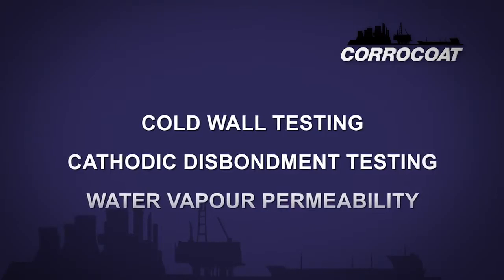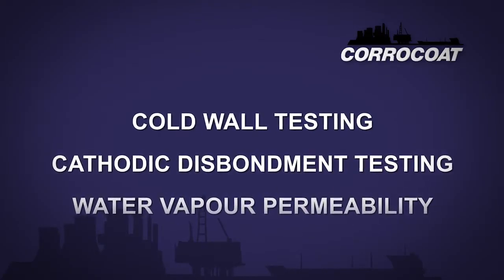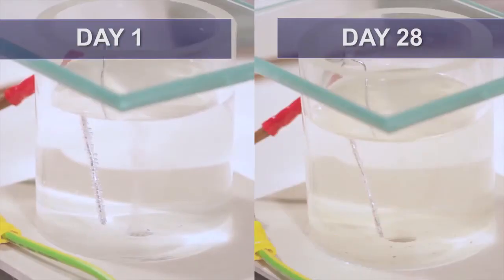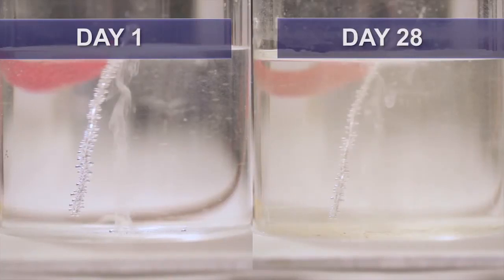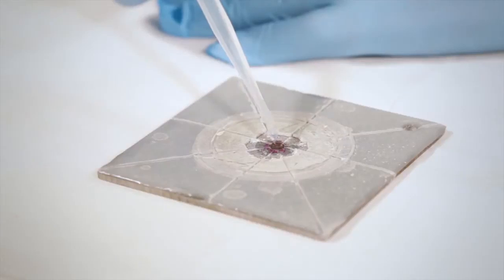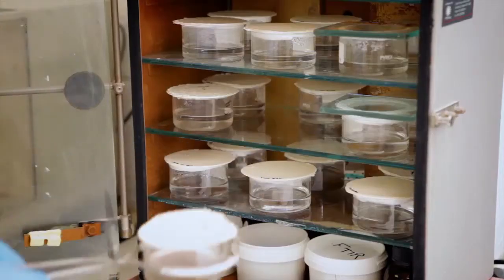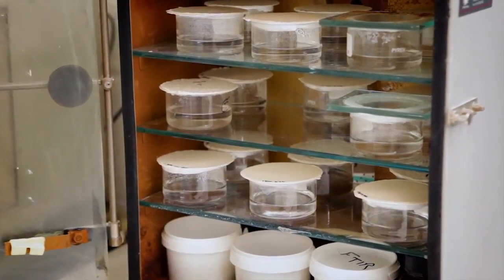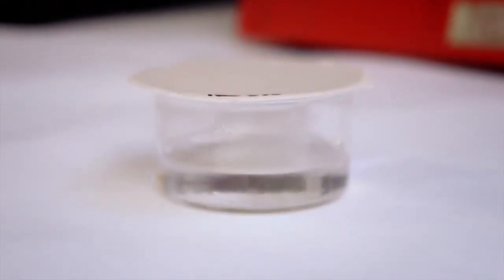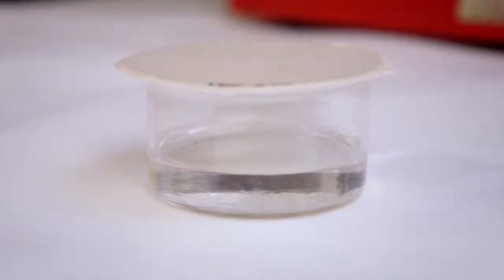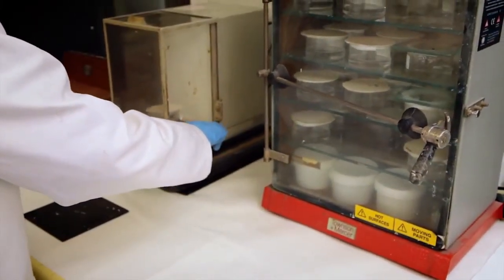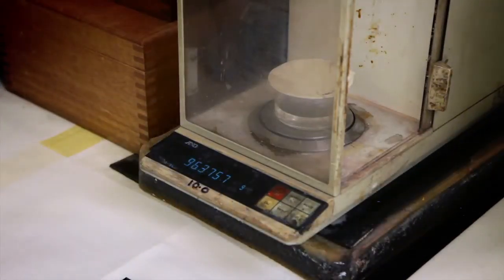I have highlighted that any test must be representative of the environment for which the coating will be in service, but there are some test protocols which have been shown to offer better data regarding the relative performance of coatings. These include cold wall testing, cathodic disbondment testing and water vapour permeability. Cathodic disbondment testing has already been highlighted in a previous Corrocoat video. This test is one of the best methods of measuring immersed adhesive strength and the resistance to undercutting from a damaged site. The resistance to moisture vapour permeation is critical for long-term performance of any coating system. Poor resistance to moisture vapour transmission results in early breakdown of the coating system and rapid failure in service. The most common test evaluation method being ASTM D1653.